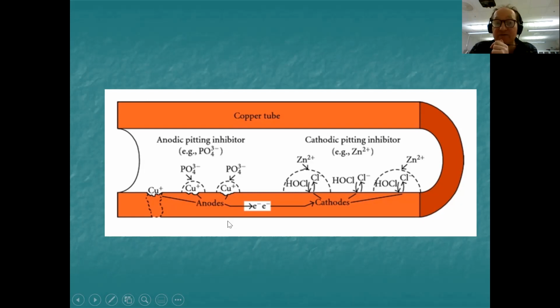So it goes in the header tank, first of all. And in this particular case, we're putting in either phosphate, which is the anodic type, or we're putting zinc in the form of zinc 2+ ions, which is clearly going to be cathodic, give cathodic protection, as we already know. And these would then react to fill up the holes where the anodes are occurring. So we protect the metal. So the cathodic inhibitor, the zinc, will go on the cathodic region. And if we put in phosphate, that will go straight to where the anodes are formed. And the two together will protect the metal. In this case, it's copper.